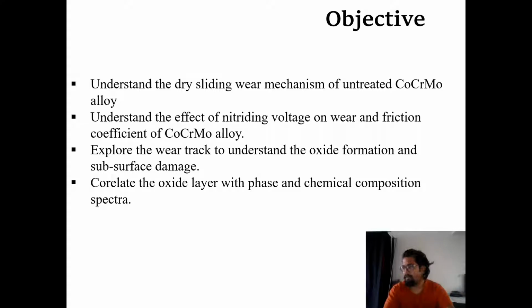I will also be discussing the effect of nitriding voltage on wear and the friction coefficient of the cobalt-chrome alloy, and further my objective here is to understand the oxide formation on the wear track and the damage below the nitrided layer or within the nitrided layer. And lastly, I'll be discussing the correlation between the oxide layer and the phase and chemical composition through Raman and XRD analysis.